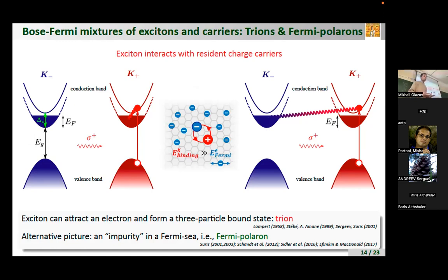And then from basic semiconductor physics, from the physics of semiconductor quantum wells, we know what in principle happens. An exciton can pick an electron from the Fermi sea and form a bound state, a trion. And then you end up with new quasi-particles, trions, which have their own life. However, in conventional quantum wells, the situation is as follows. The exciton binding energy is about 10 milli-electron volts. There could be deviations, smaller or larger, but something like this. The trion binding energy is 1, 2, 3, 4 milli-electron volts. And this is more or less the scale of disorder in the system.